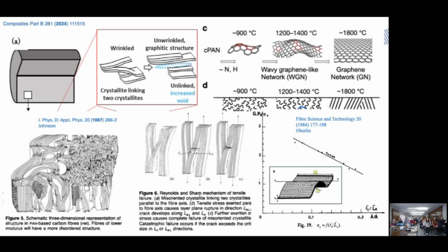One way I would explain this is let's step back. Have any of you guys ever split a piece of wood with an axe? If you have wood with really oriented grain, it's far easier to split. But if you have wood with some gnarled character to it, you're going to have to wrestle to get it to split. Somewhat analogously, that's what's going on in these carbon fiber structures. The issue is you need material that is resistant to the propagation of cracks, in this case very micro cracks. That's what gives you the high strength and high strain to failure of these pan-based fibers compared to very graphitic fibers like the mesophase pitch fiber.